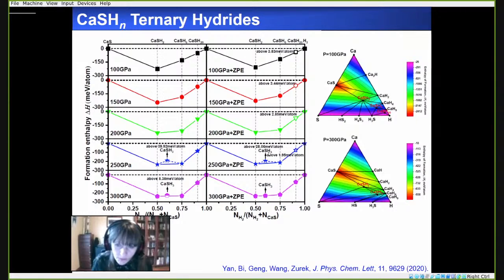CaSH3 is metastable. At high pressures, it is stable. And here I show the convex hull, including the zero-point energy. It's really important in a lot of these hydrogen-rich structures to consider the zero-point energy, because they have so much hydrogen within them that this can actually change the thermodynamic stability, or change which structures are thermodynamically stable.